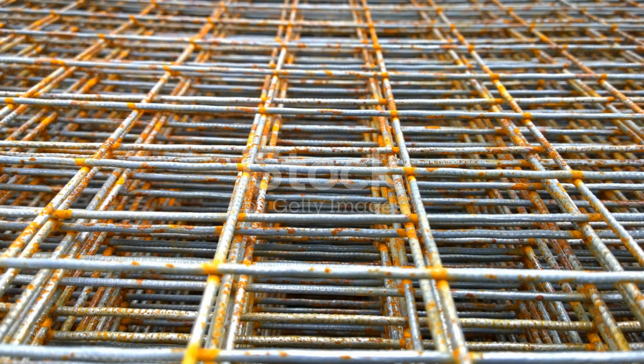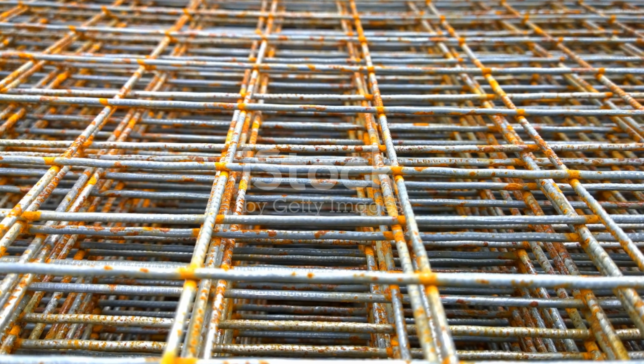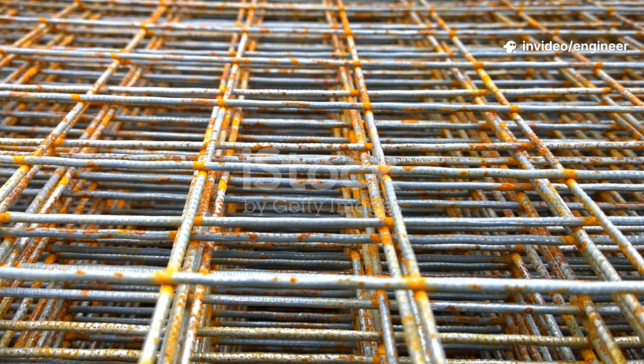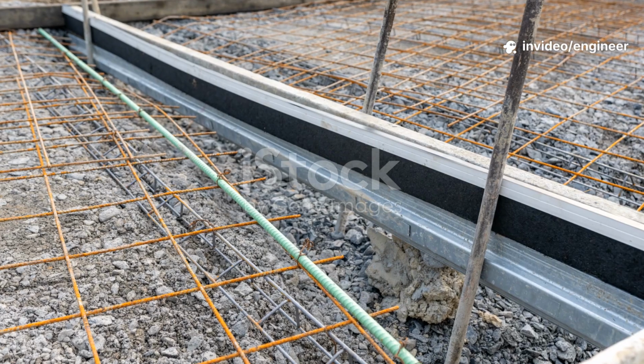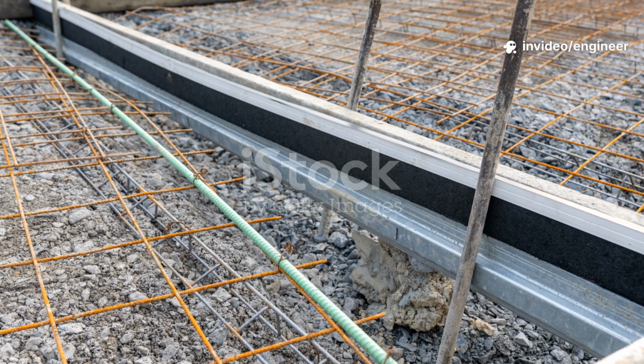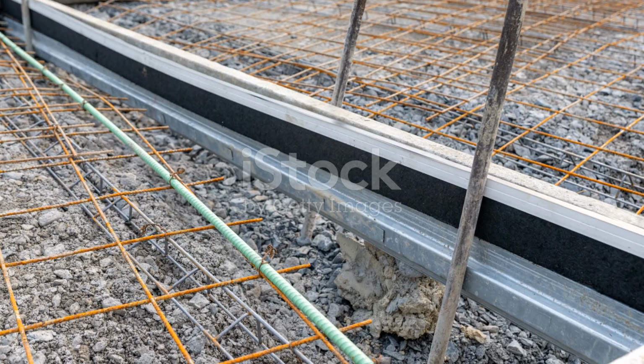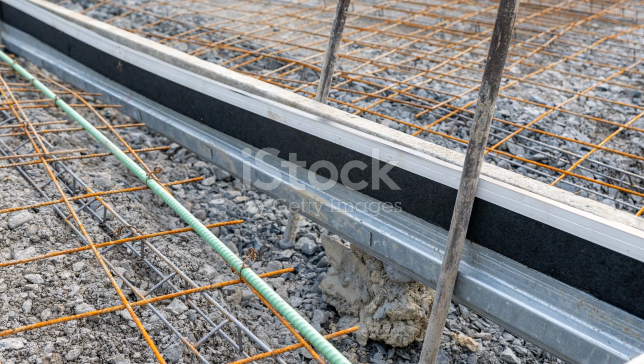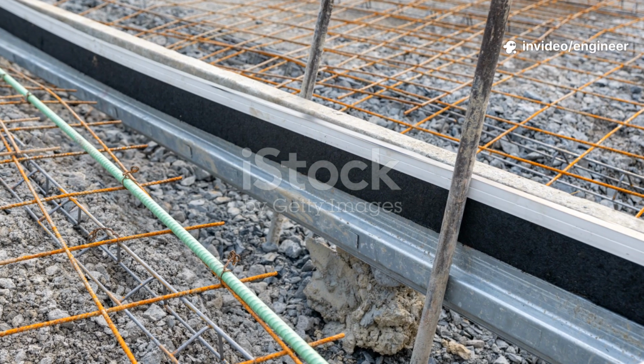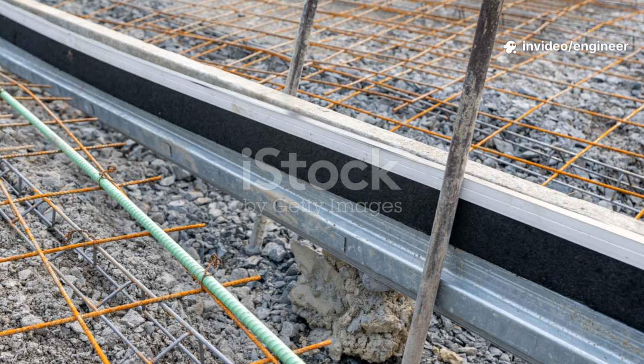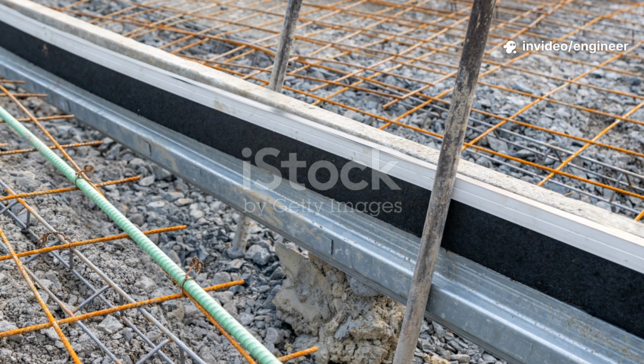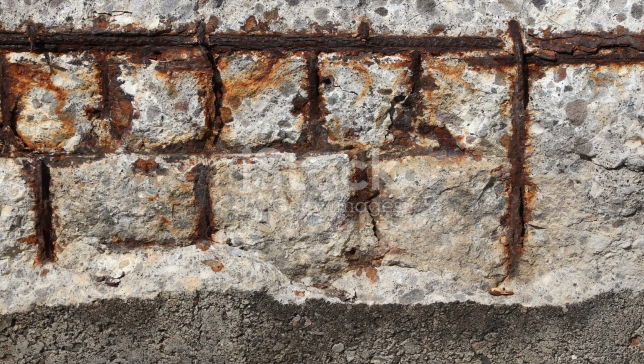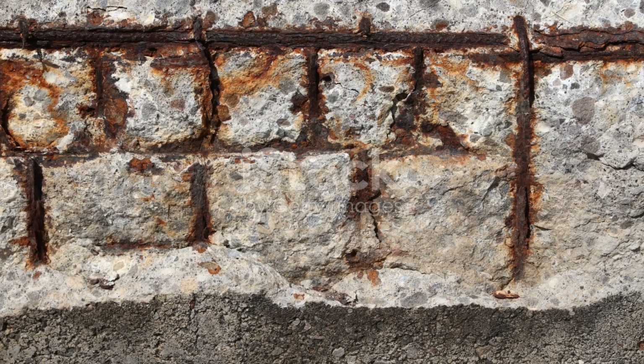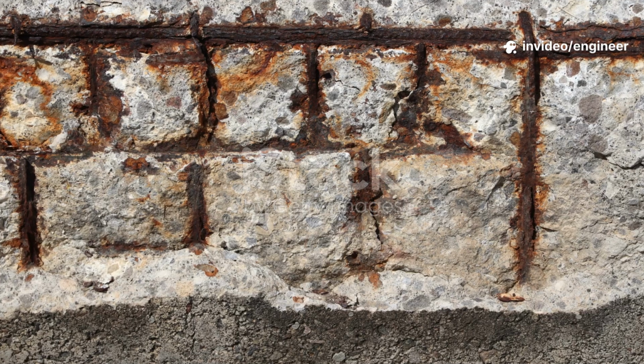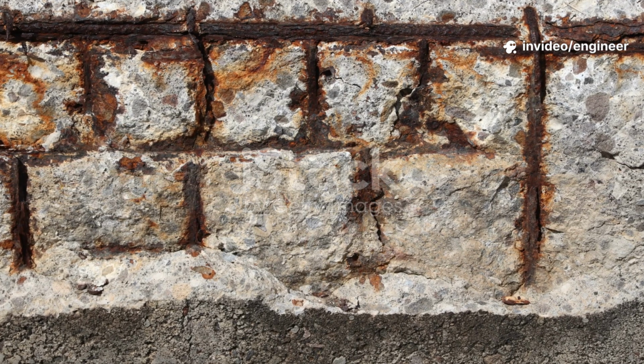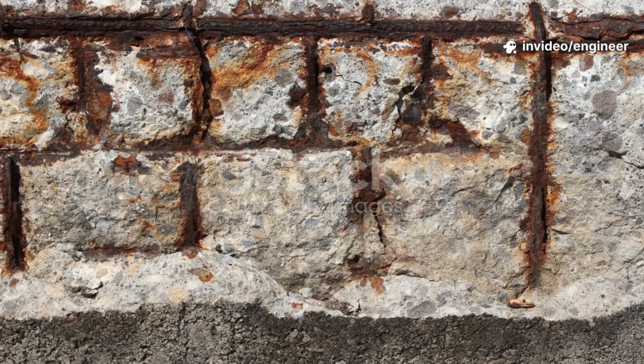Beyond detailing, two other fundamental mistakes can cripple a shear wall: incorrect rebar placement and poor quality concrete. The rebar grid is the wall's skeleton, providing tensile strength to resist cracking under load. For this skeleton to work, rebar must be placed exactly per the design. Correct bar diameter, precise spacing between bars, proper concrete cover, the distance from steel to outer surface. Bars spaced too far apart leave large unreinforced concrete sections prone to brittle shear cracking. Bars too close to the surface, with insufficient cover, are vulnerable to moisture and air, which leads to corrosion.